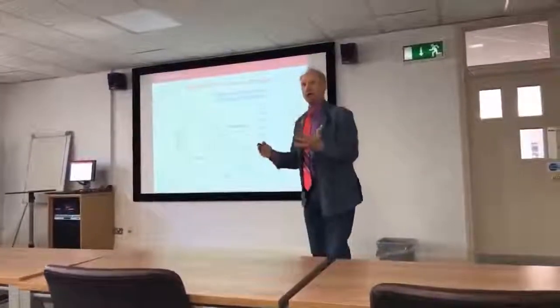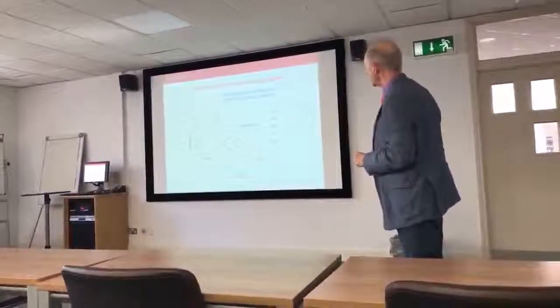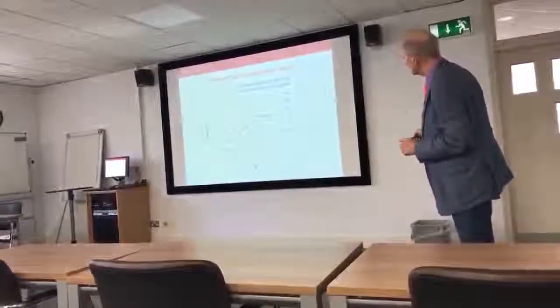Well, we're not really interested in lifetime per se. We're interested in this KNR value, so the rate constant. So we calculate the rate constant, as I mentioned on the earlier slide, just by comparison, eliminating the oxygen and using a measurement of the low temperature lifetime. Subtract that away, and now this is an Arrhenius plot of the log of the non-radiative decay versus a normalized inverse temperature. And again, we've normalized it to TG, so this is the TG right here. This is temperature below the TG, so this is all the glassy state. And what you see is this non-Arrhenius behavior, curvature within the glassy state.